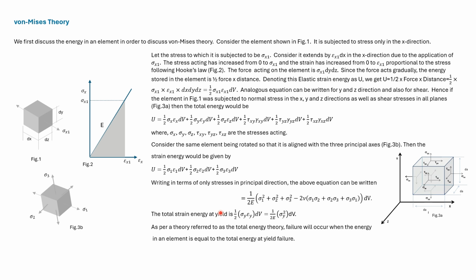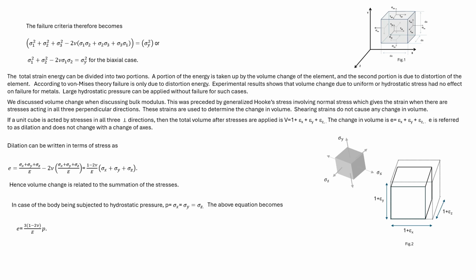Consider an element to be subjected to one stress only, and that one stress is taken up to yield. Then the strain energy as per this term will be given by the left hand side of this expression. Substituting epsilon in terms of sigma and E, we get this expression for total strain energy at yield. As per total energy theory, when the total strain energy as given by this expression equals the total strain energy at yield, then the element fails. Equating the two expressions, we get this equation which gives the failure criteria according to total energy theory.